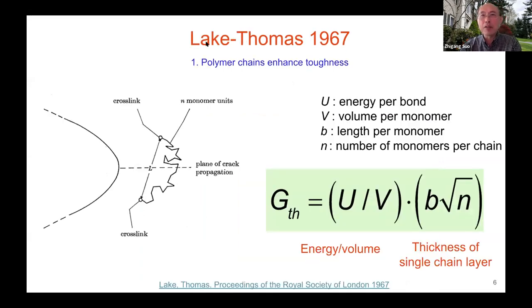Now, I want to spend more time on this Lake-Thomas model. It's almost like an orphan. The paper is not extremely highly cited. It's well cited, but disproportionate to its contribution. It really underlies all polymer fracture. But these gentlemen were working on elastomers. They have two insights, so I have two pages. Insight number one: polymer chains enhance toughness. You don't need plasticity, just the chain itself. Why? Because you need to break this chain. Here's a chain. This chain has very strong covalent bonds, as strong as glass. It's a carbon-carbon bond, as strong as any covalent bond. But in between chains, one chain and another chain, the interaction is weak.